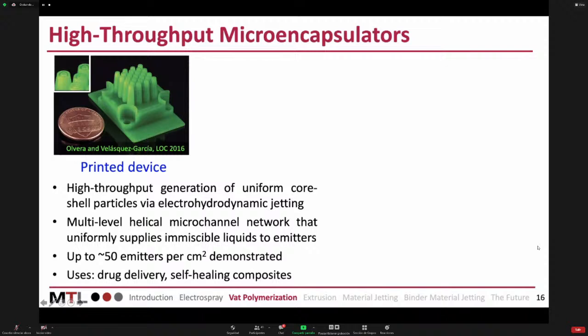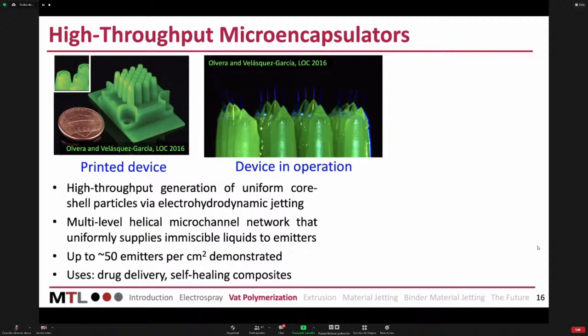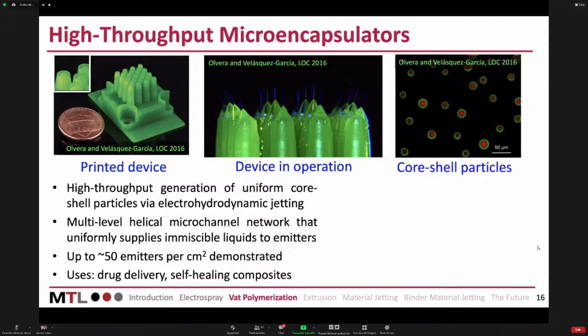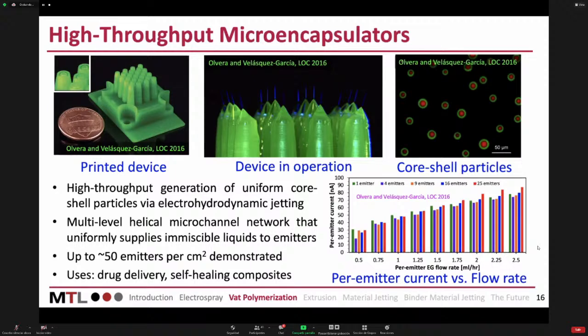Another example is microencapsulation, something I mentioned at the very beginning. And you see that they're working uniformly and producing these core shell particles. What I wanted to say here is that you really see that they are uniform because this is a plot of how much current each of the emitters is producing versus the flow rate. And you see that they closely match. So there is this shape that is a square root that is predicted by the physics. But what is important to see is that even though you have a wide variation in the number of emitters, the per emitter performance is very similar. So this talks very well about what you can design in these devices.